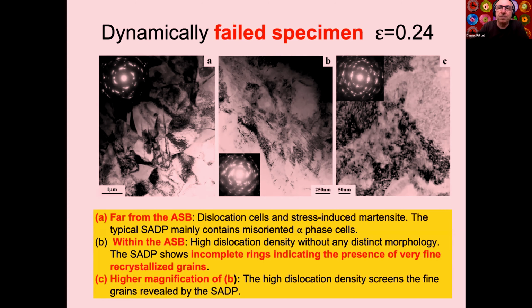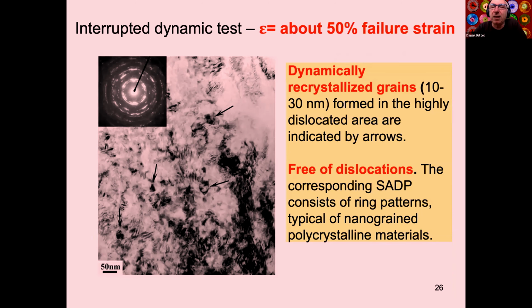Okay, that's not new. What is new is what I'm going to show you here, because this specimen was not broken. It was loaded up to only half of its failure strain, stopped and sectioned. If there was a small temperature rise at failure, at half of the failure, there was no temperature rise. But again, look at this diffraction pattern, and you see your nanograins are here again, and you can see some of them. So in fact, you can understand that nanograins formed way before failure. And you can go even beyond and say that, in fact, this phase transformation is the precursor to failure.